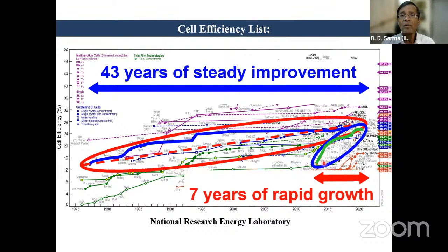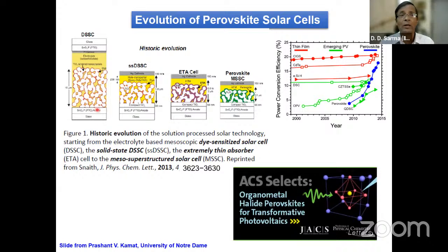Not only the efficiency, it turns out that this material is a fantastic absorber of light, because silicon is a very poor absorber of light. You need to make it quite thick, and making it thick makes it more expensive, heavy, more breakable, and all kinds of problems. So people are looking at how to make it thin. One of the technologies that was proposed is the dye-sensitized solar cell, and it was shown that you can make the device as thin as 10 micron. Then came the solid-state dye-sensitized solar cell, and one could bring down the thickness to about 2 micron. Then that same technology evolved into extremely thin solar cells, which became about a micron thick. And the technology based on this material can be as thin as half a micron thick. So you can see that it is a fantastic absorber, so you can make an extremely thin solar cell and still have very good efficiency.